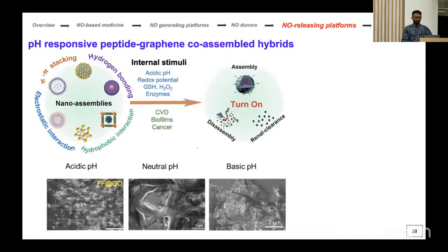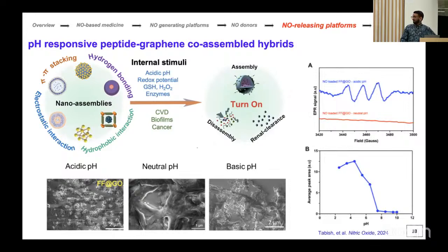We use that peptide, and we show that at neutral pH you see a sheet-like structure, but under acidic conditions you can clearly see that these assemblies are disassembling. Then we show that under neutral pH this supramolecular assembly is not releasing any nitric oxide, but under acidic conditions it does. Then using electron paramagnetic resonance, we show the average peak area calculated from EPR to show how much NO is released under different pH, and you can see that it is primarily released under acidic conditions. This brings me towards the end of my talk.